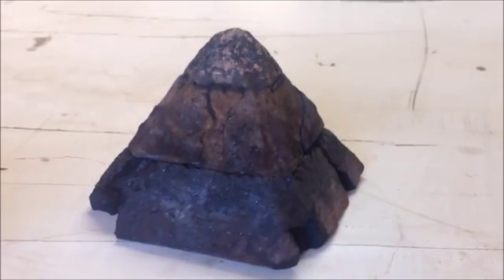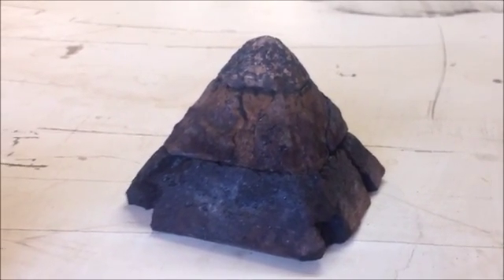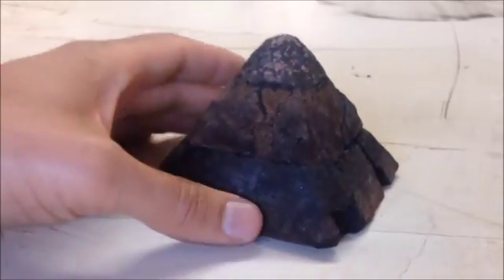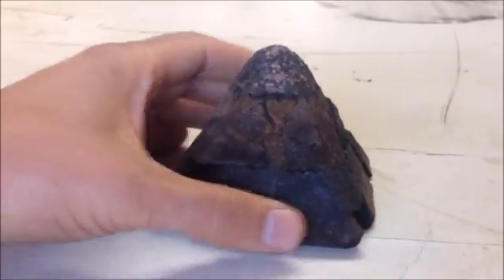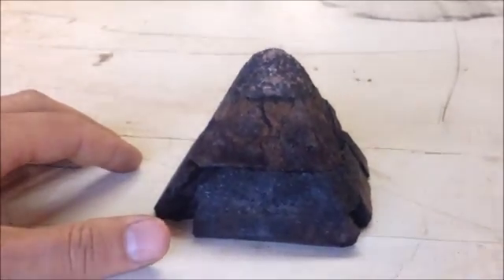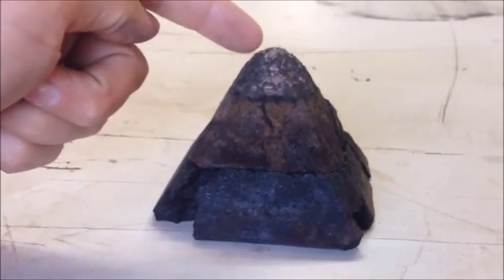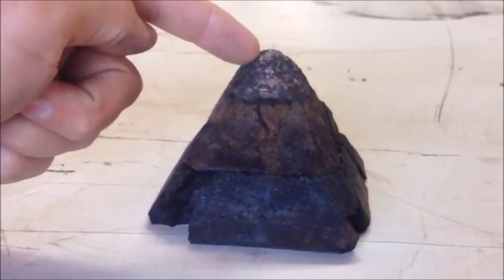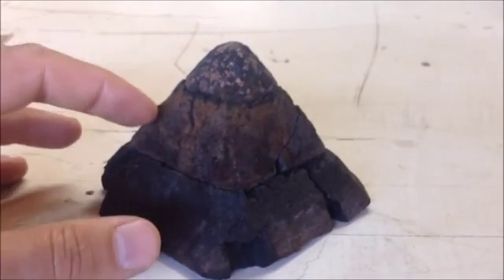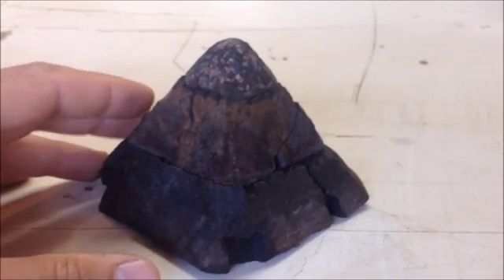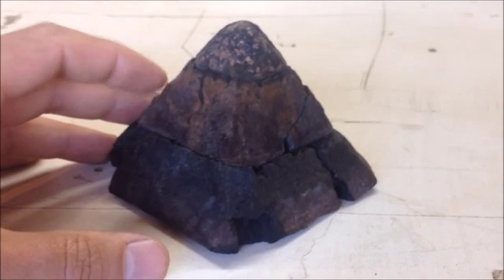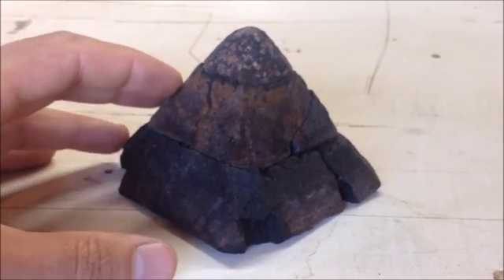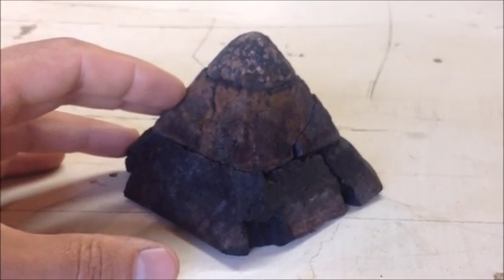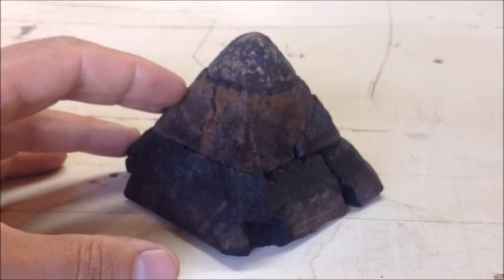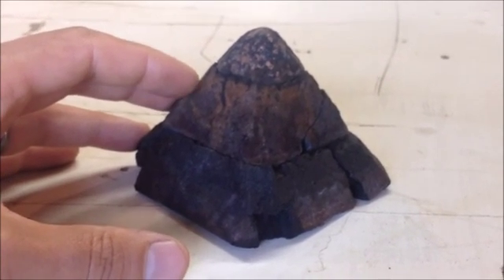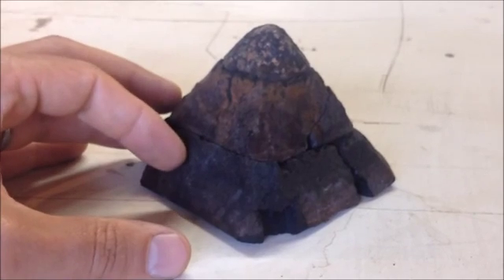Now here's a separate smelt I did on the mat that was recovered from the first smelt we did. So I took all the mat from the first smelt, broke it off, and re-smelted it with some potassium nitrate and iron filings. And you can see I didn't use any copper, but we recovered quite a bit more copper from the mat. By adding iron filings to the smelt, the iron removes the sulfur from all the different types of sulfides in the mat and forms FeS, which is then soluble in the slag.